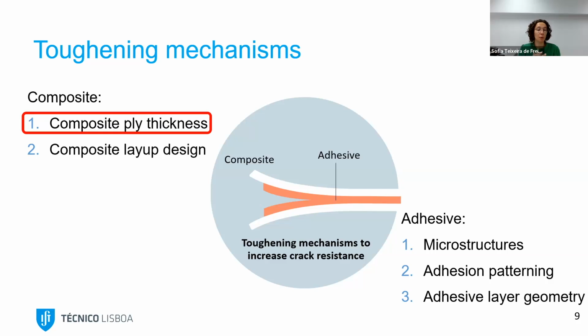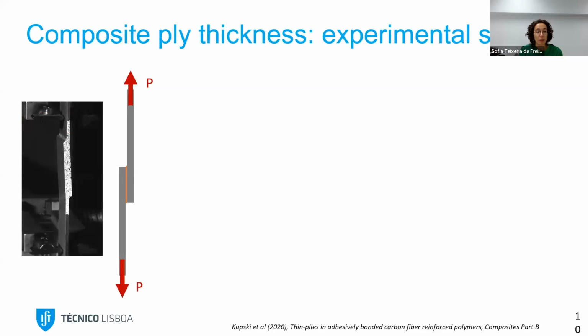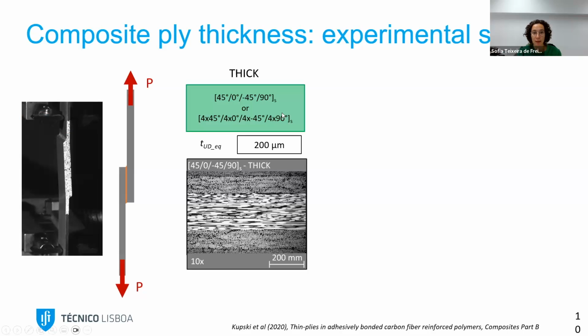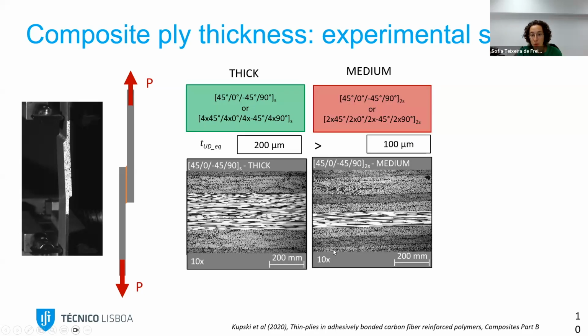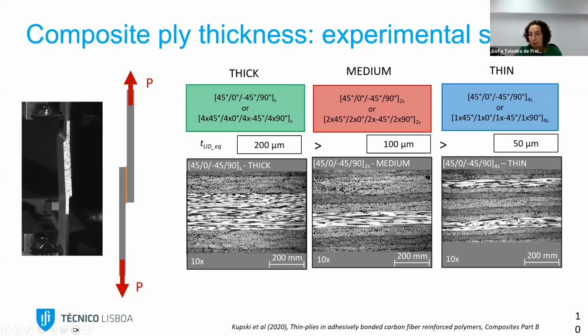And the first parameter that we tried to change was the ply thickness. So here you see a single lap bonded joint, which was tested in tensile load. Here you see the schematic. Here you see the test in itself, the specimen, with the DIC speckle pattern. And what we varied was the ply thickness. What does this mean? We called the specimen which was thick, the one in which we had a 200 microns ply thickness. And then we decreased the ply thickness to 100 microns and 50 microns.